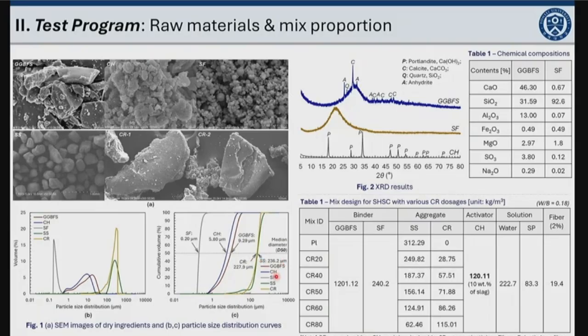The silica sand was progressively replaced with the crumb rubber up to 80%, with an interval of 20%. The amount of calcium hydroxide was determined to be 10% by weight of the slag, based on preliminary tests for pH and chemical concentrations in the pore solution and thermogravimetric analysis.